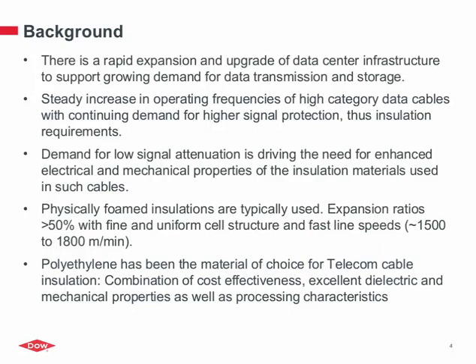Physically, there are other methods, but for this particular application, physically foamed insulations are typically used, and I will say more about that and the reasons why. Expansion ratios of about 50% and greater are generally used, and what is demanded are fine and uniform cell structures. These are cables which are a very thin wall. Generally, the insulation is under 500 microns, and therefore, if we are foaming within 500 or less microns of insulation thickness, you can imagine that the insulation structure has to be accordingly fine.